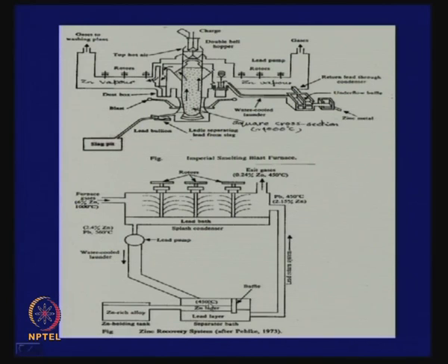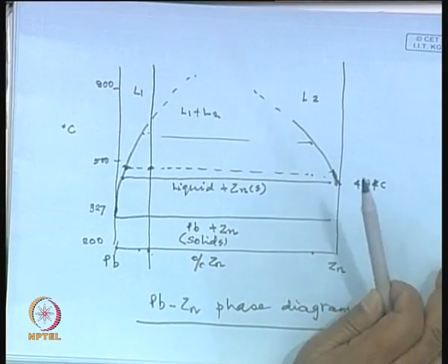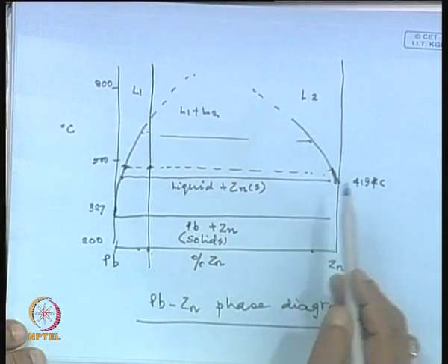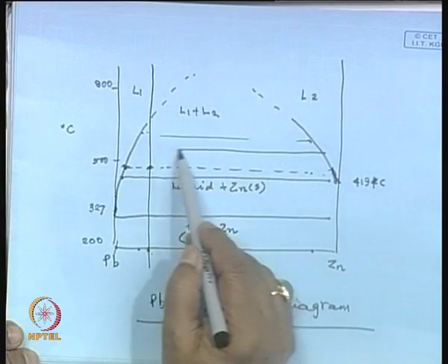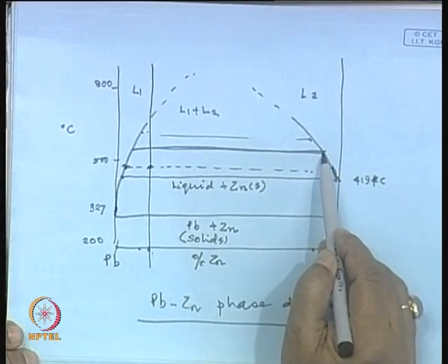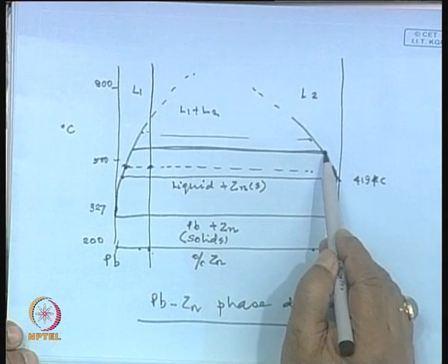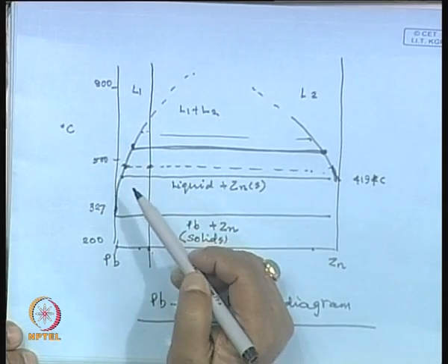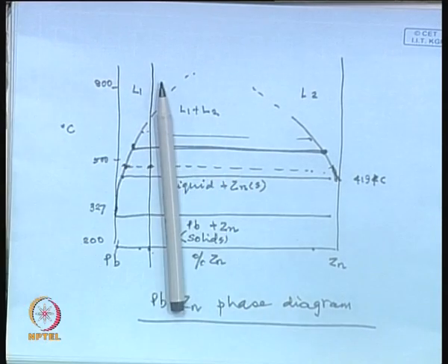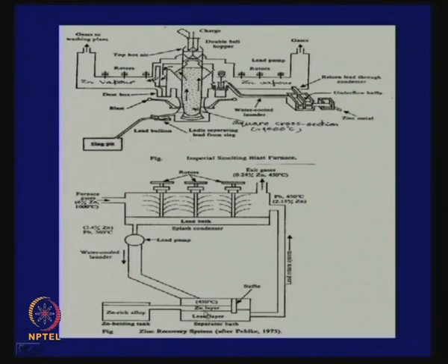It is cooled to 450 degrees, and immediately two separate layers come out, liquid lead and the zinc layer as per the phase diagram. If you go back to the phase diagram, if you come down to about 450, which is slightly here, you are getting one liquid of this composition, another liquid of this composition. And so, two layers are coming, one zinc layer which is almost pure zinc, and a lead layer which has very little zinc.